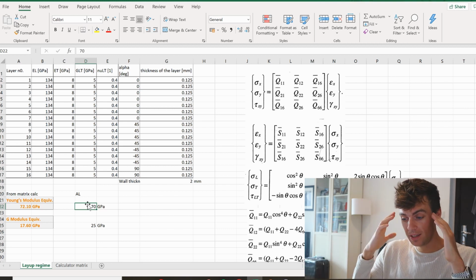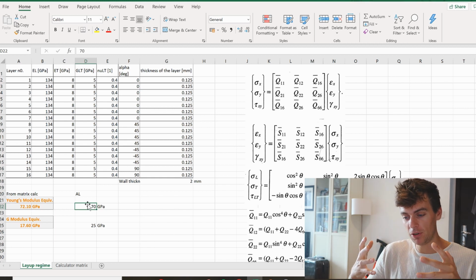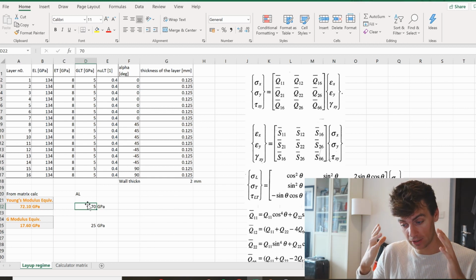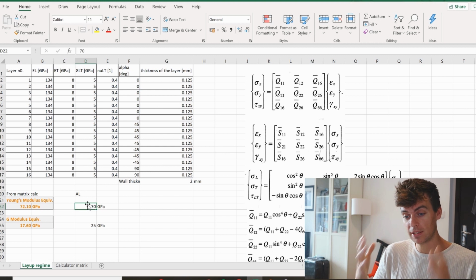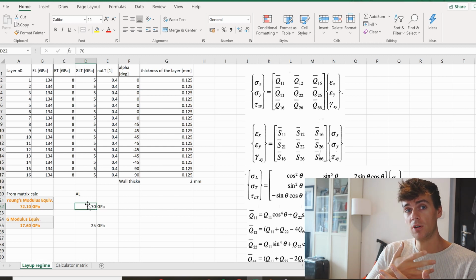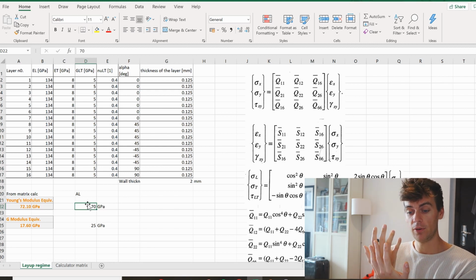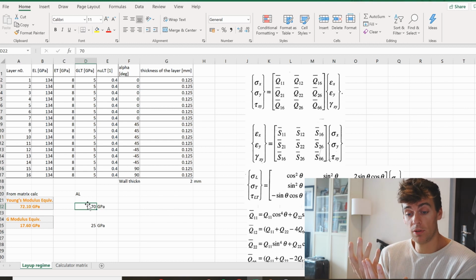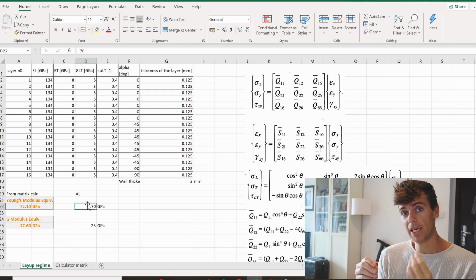Now, if you haven't thought about this laminate approach, that seems mental, but I can assure you that's what happens. You get this stiffness dilution as you lay fibres off the 0 degree axis to loading, and it's just not as stiff as you thought. So how can you deal with this? Well, you can make the wall thickness bigger and still have the carbon fibres much lighter.